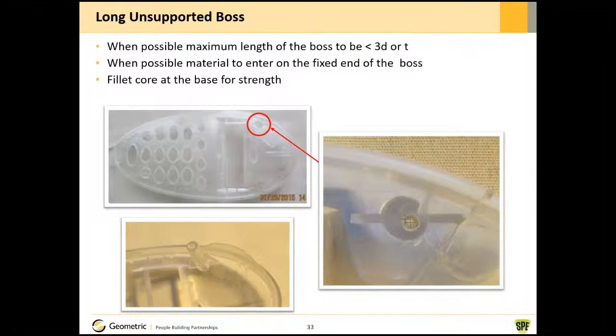Long unsupported bosses. So here's a part which has a long boss here. You can see this long boss here. We want this length to be no more than 3 times the diameter or 3 times the thickness, but here it's about 10 times. And this is a cross section of the boss. This is the outside of the boss. You can follow my arrow. And this is the hole inside the boss. Now you can see these are not concentric. They're supposed to be concentric.